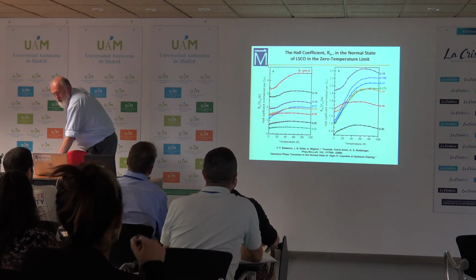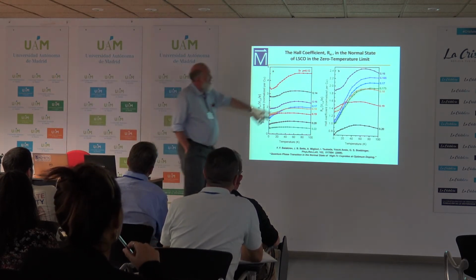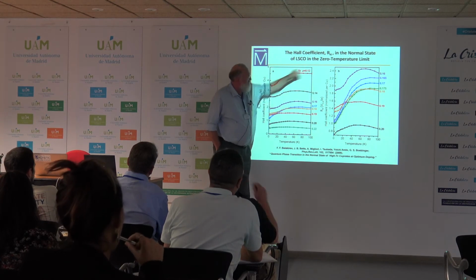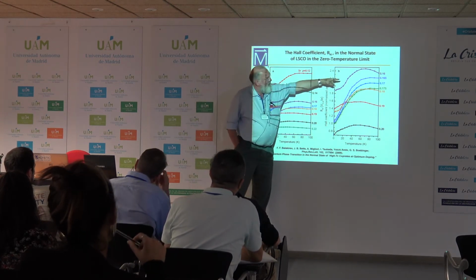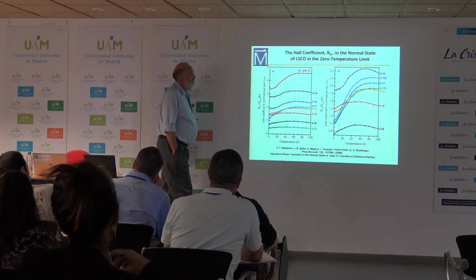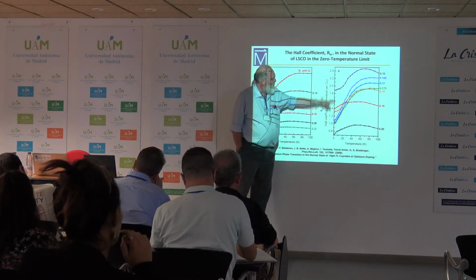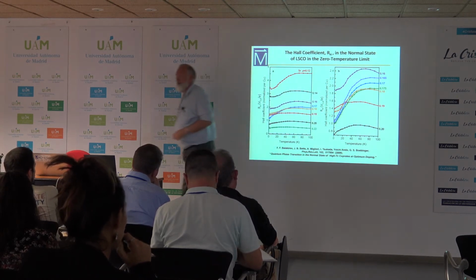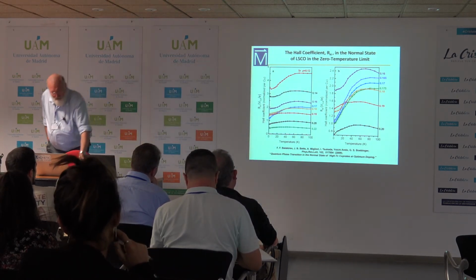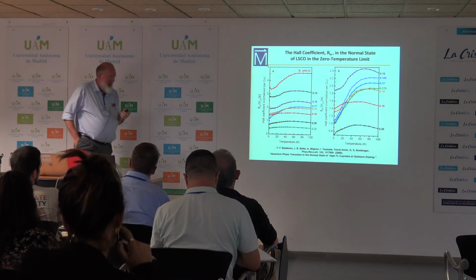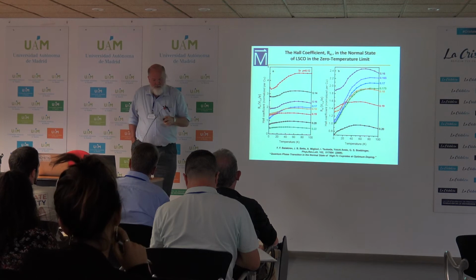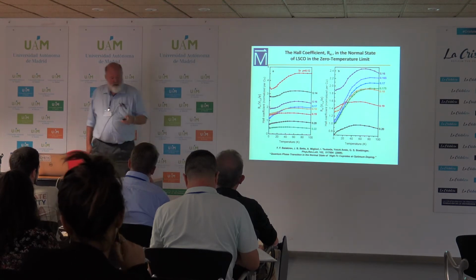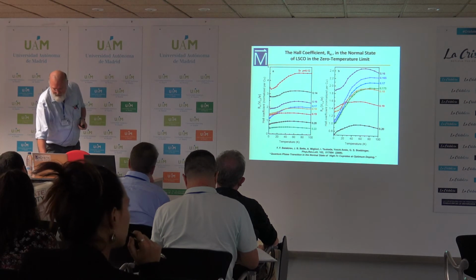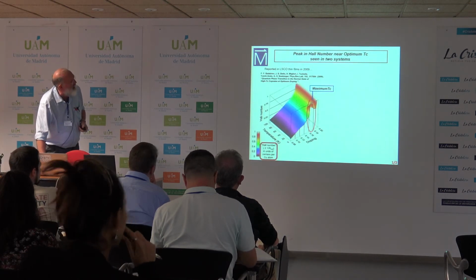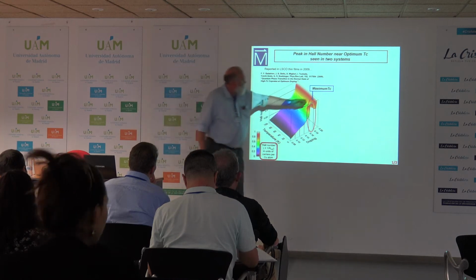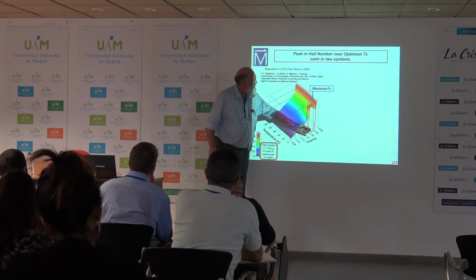Now, it's not just the one curve. We took many more curves. So here, these are the same data, just plotted on different axes, but we've added the data at 0.165, at 0.175, and so you can see there's quite a few samples that show this non-monotonic behavior that gives rise to this peak. So a peak in the Hall number gives some evidence that there's something dramatic happening to the Fermi surface, some sort of phase transition occurring in the system right near optimum doping. In fact, maximum TC is sitting at right 0.17 in this sample.